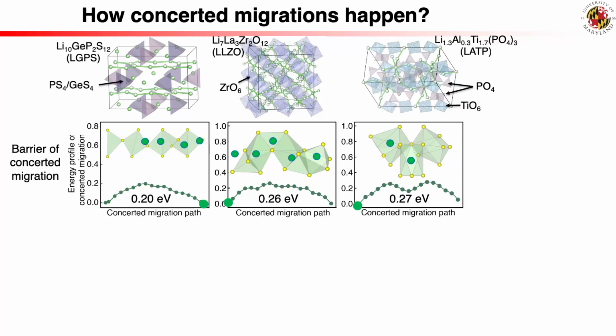What about LLZO? In LLZO, the lithium ions are distributed between tetrahedral and octahedral sites. The concerted migration they saw involves the lithium ions in tetrahedral sites hopping to nearby octahedral sites, and at the same time, the lithium ions in those octahedral sites hop to their neighboring tetrahedral sites. So it's like a coordinated exchange, a real atomic dance.